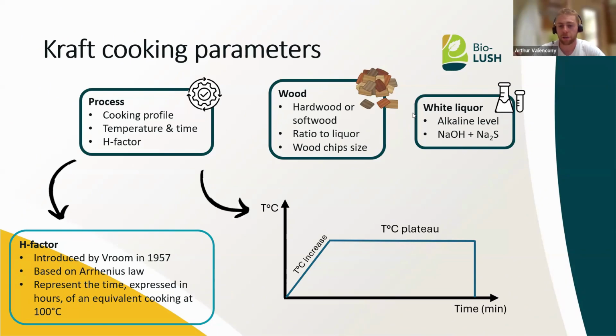And finally, the white liquor, meaning the chemicals introduced into the kraft process. The kraft process is an alkaline process with sodium hydroxide and Na2S introduced, which are the two main components of the white liquor. And obviously, you can also add water to control this liquor to wood ratio parameter. We can see, for example, a cooking profile where we have a controlled temperature increase with a plateau at a certain temperature, which can be, as Sandra said, between 150 degrees and up to 170. At the end, the wood chips, which have been converted into pulp, are defibrillated, and the pulp is cleaned to eliminate the black liquor.